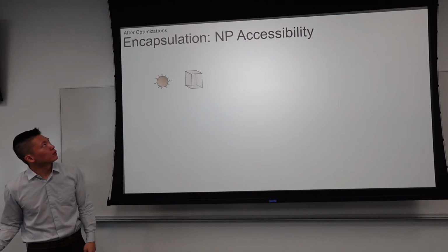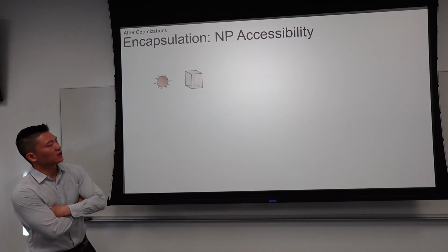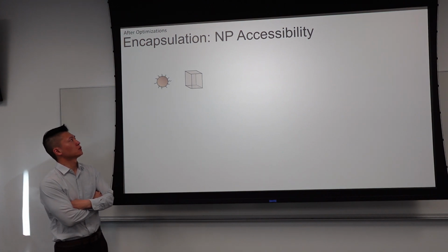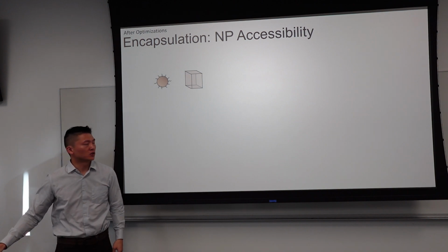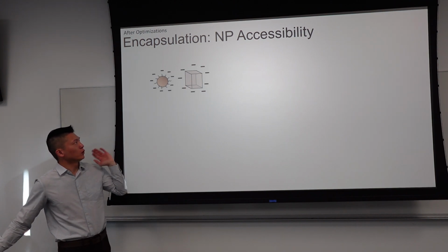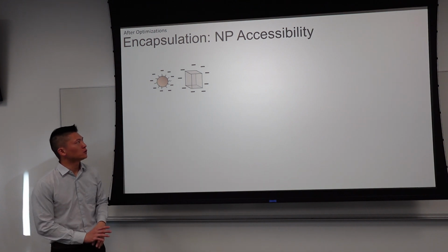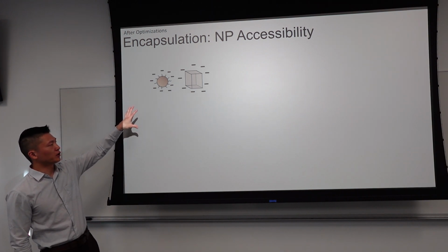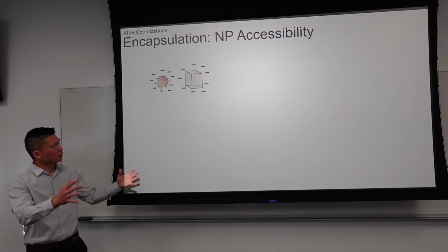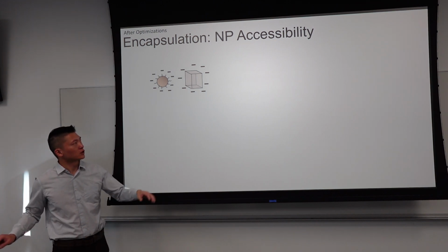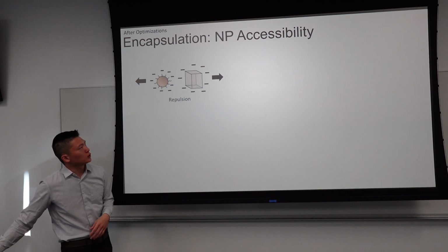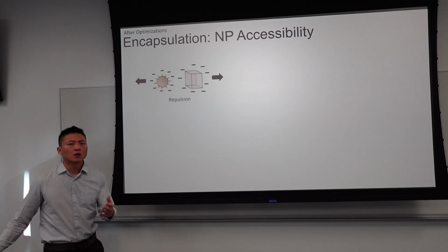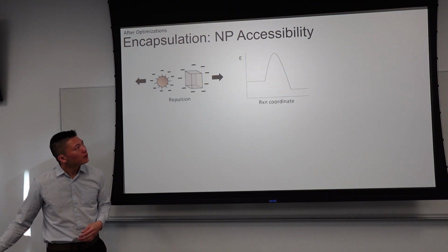Again, this increasing intensity is the result of encapsulation. Okay, so if I'm able to get optimizations, my next step would be to study how this nanoparticle encapsulation is occurring with the DNA origami cage. First off, we know that these particles are negatively charged, because DNA is negatively charged. So the ligand shell here would give the surface of the nanoparticle a negative charge, and of course the DNA itself is negatively charged. So we do expect repulsion. Of course, this is in solution, so we do expect DLVO effects as well.